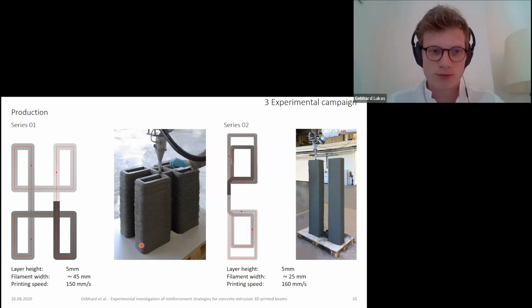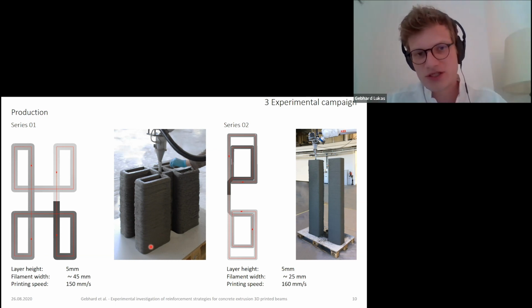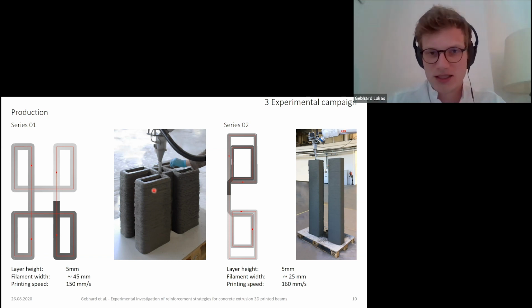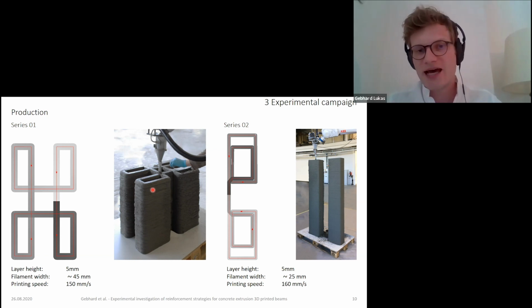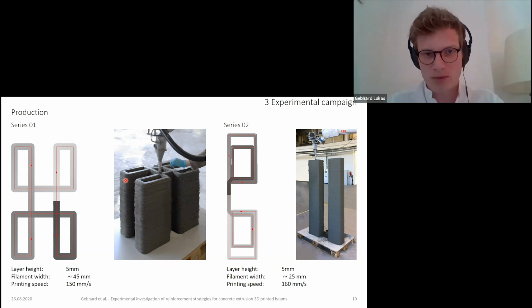So on the left 2 pictures, you can see the print path and a print image from the beams of series 1. So you can see that we have the 1 void in the middle, and we only printed half beams for this series. So we always printed 2 half beams without transversal reinforcement and 2 half beams with transversal reinforcement. They had a layer height of 5 millimeters, and there was 1 filament with a width of 45 millimeters and a printing speed of 150 millimeters per second.